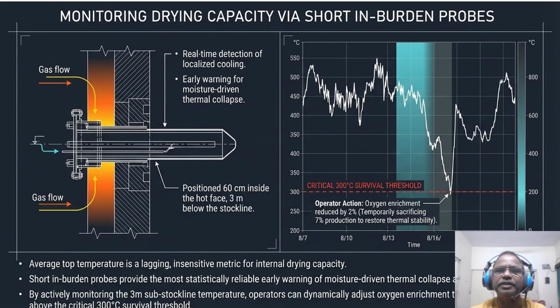When that probe temperature dips towards 300 degrees centigrade, as seen around 8/16, it is an early warning of the moisture-driven thermal collapse at the wall. In this specific case, the operator reduced oxygen enrichment by 2%, sacrificing 7% of the production to restore thermal stability. So it's a high price to pay, but it prevents a total furnace freeze. By monitoring the 3-meter sub-stock line temperature, we move from reactive to proactive engineering.